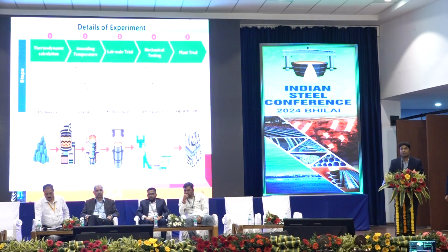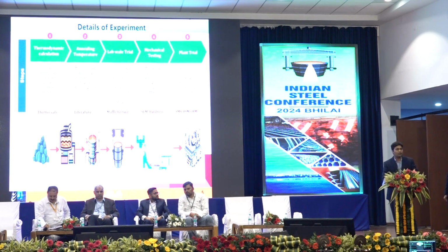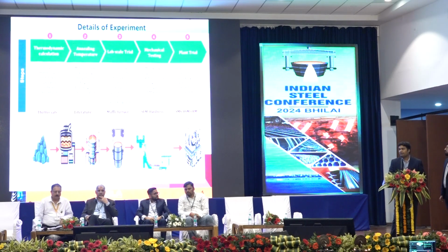So there were recent collapses of structural bridges. One of the proposals from the railway, mostly the RDSO, was how can we substitute this carbon steel with stainless steel? Keeping that in mind, we developed one grade which has similar mechanical properties and impact toughness as the carbon steel and has better corrosion resistance and also a lower life cycle cost.